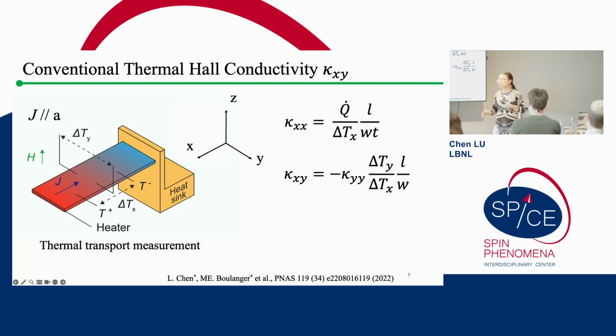So this figure clearly shows that the thermal Hall effect is just the thermal analog of the electrical Hall effect. For electrical Hall, you give it an electric current, you put in the field, and you get a transverse voltage difference. For thermal Hall, you put in a heat current, and in the presence of a field, you get a thermal gradient transversely. With this setup, we were able to measure both thermal conductivity and thermal Hall conductivity simultaneously.